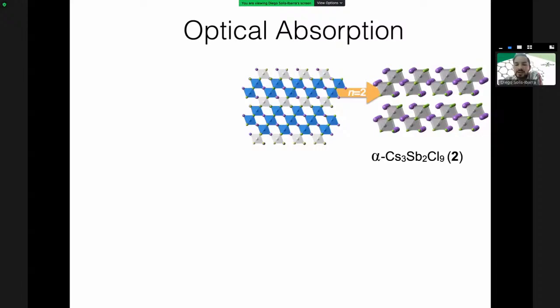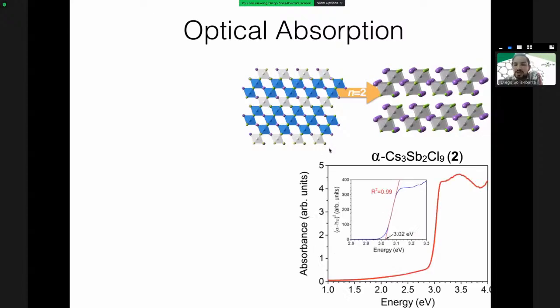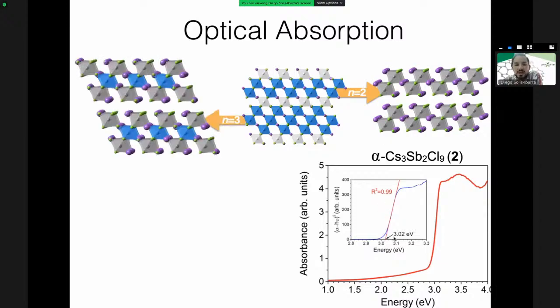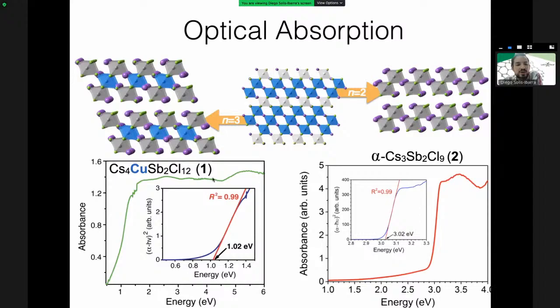And what was really surprising is that the parent material, the one which has only antimony, has a really large bandgap of about 3 electron volts. But what we found is that our material, once we incorporated copper, has a much smaller bandgap of about 1 electron volt. So this is a really drastic difference between these two materials. And of course, when you're talking about 1 electron volt, you're around the region where making solar cells becomes something interesting and definitely possible.